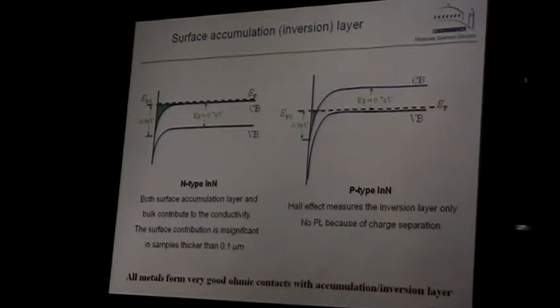The problem is the following. Even if you make solar material P-type and N-type in the bulk, the problem is the surface. The surface always has defects. Because on the surface you cannot eliminate defects, this is a natural feature of the surface. So of course if you have defects on the surface, the Fermi energy would like to be high above the conduction band. It means that you have accumulation on the surface. So there is a large layer with a large concentration of electrons.